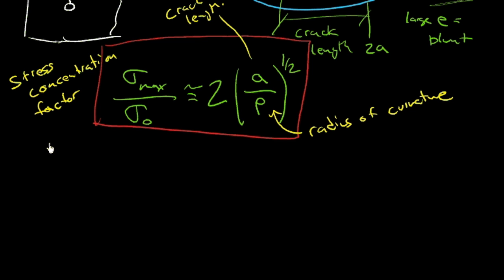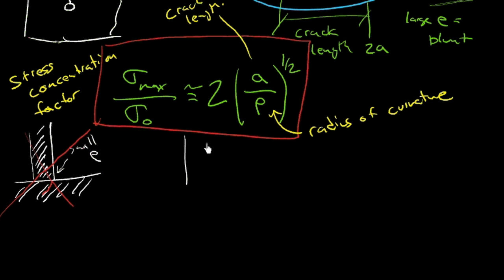I mean, that's actually also useful in mechanical design, too. Say you've got some base onto which you're going to weld, or you're going to machine or fasten some kind of an upright. Well, if you design it like that, you might design it in your CAD software, and you find that you've got the dimensions exactly the way you want. But what you've done, if you're not careful, is you've designed a small radius of curvature on this inside corner. And what's going to happen is you're going to get cracks initiating and propagating from that sharp inside corner. So what do we do? So instead of doing that, well, good design practice is instead to go like this. And you design in what we call a fillet radius. So you design the largest radius for that inside corner that the design will tolerate.